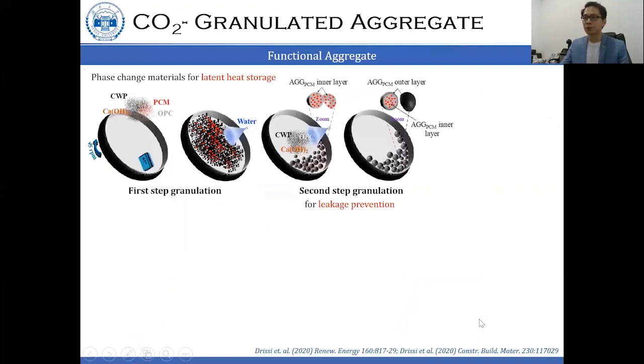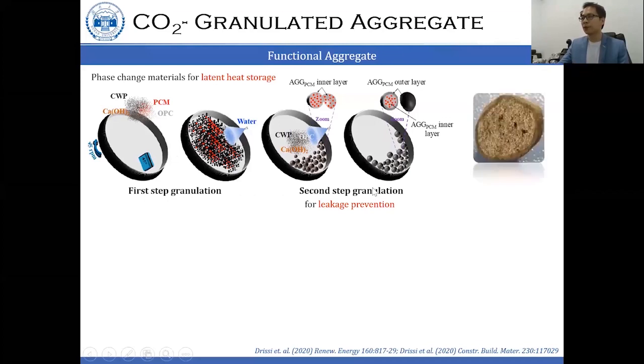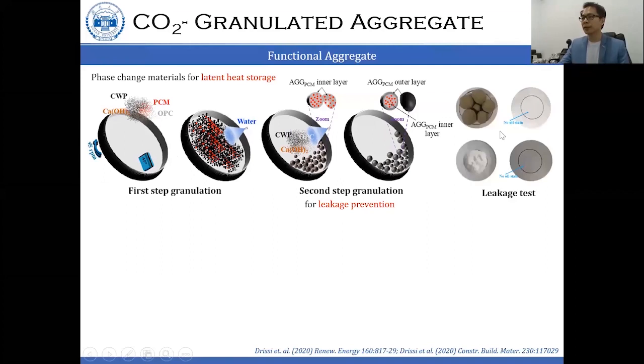And we're also using the granulation process to incorporate some smart material, for example, phase change material for latent heat storage. So we'll apply PCM with other raw material during the first step of granulations. The second step of granulation, the main purpose is to make a shell layer to protect the leakage of the PCM. So this is the aggregate. We can see they have a clear, obvious difference between the core and the shell layers.